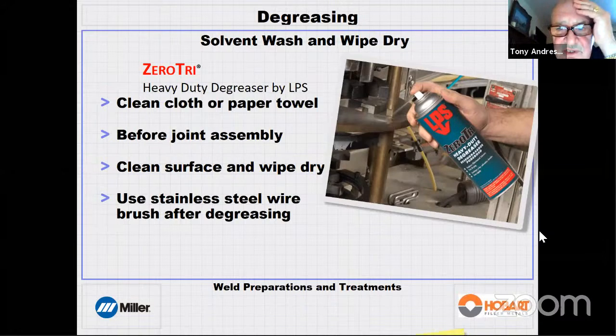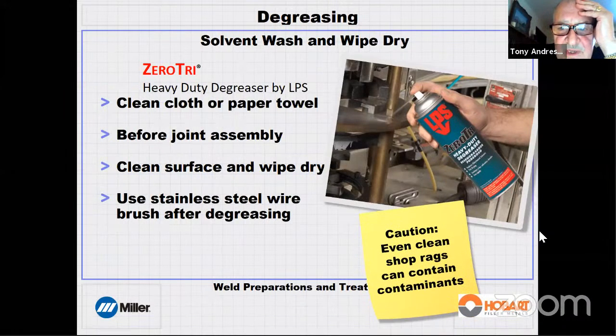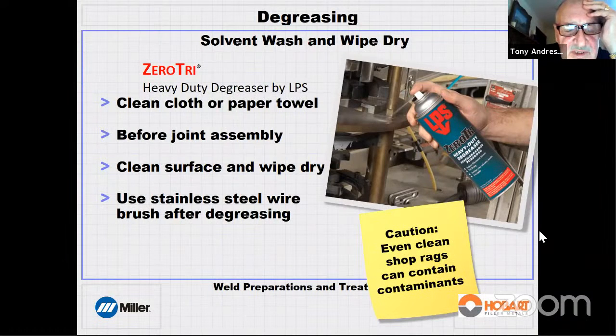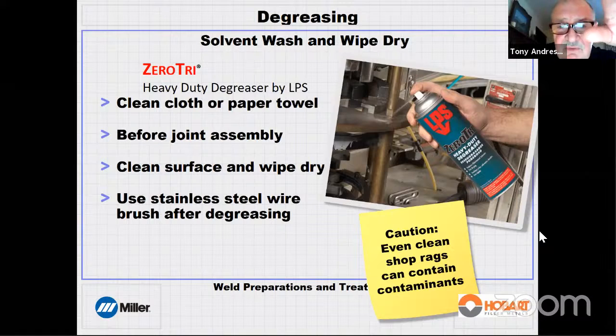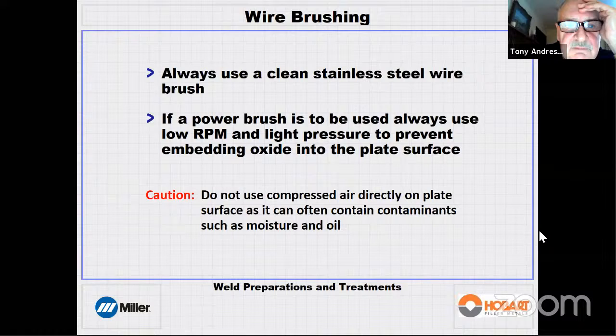This is a good solvent we use here in the States, made by a company called LPS, called Zero Tri. You can spray it on the surface of the material or on a paper towel, is what we normally use, and wipe down the surface, and that will get rid of hydrocarbons. And that is the first thing you do before you wire brush. You will always degrease before you wire brush. Otherwise, you can take the contaminants on the surface and put them into the subsurface when you wire brush, and also contaminate your wire brush.